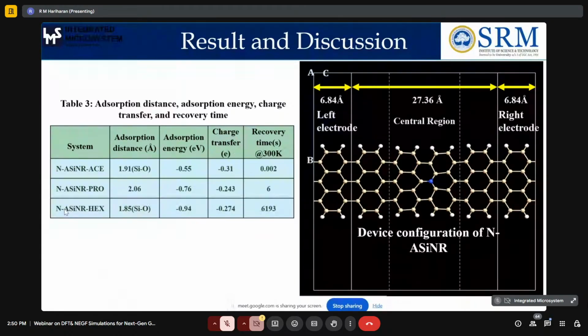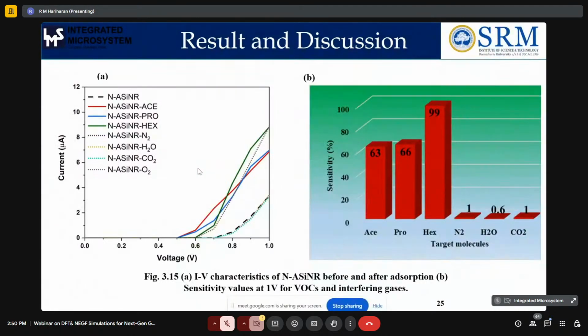Keeping this in mind, we took the three systems and converted them into a device. Now a two-probe device has been set up for these three devices, and we performed the IV characteristics. Through IV characteristics we calculated the sensitivity, and what we can see is that the sensitivity for hexanol is very high when compared to that of propanol and acetone.